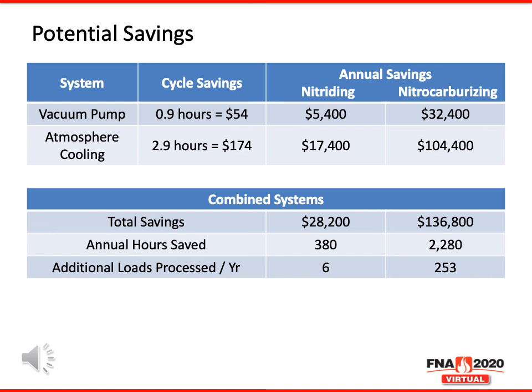So if you were to translate that into additional loads processed per year, and then think about the additional revenue that can then be generated without needing to necessarily add additional furnace capacity, you're looking at an additional 6 cycles a year on the nitriding side. It doesn't sound like much, but it does add up over the course of time. And on a nitrocarburizing cycle, you're looking at significant, potentially 250 or so additional loads processed per year. So there's a potentially sizable amount of additional revenue that could be added to your operation without necessarily adding additional furnace capacity.